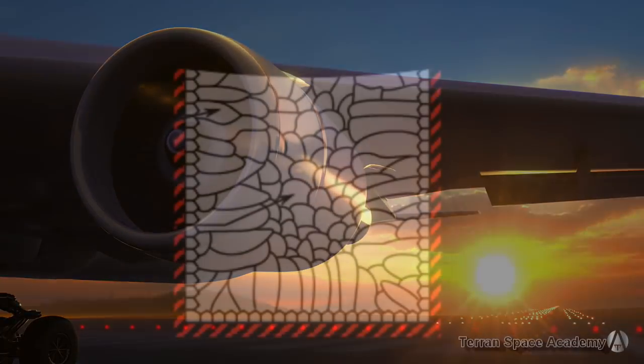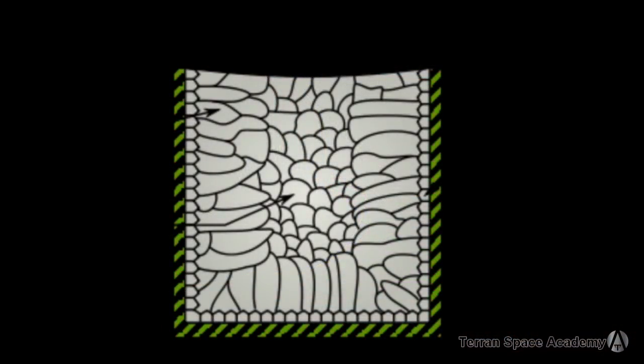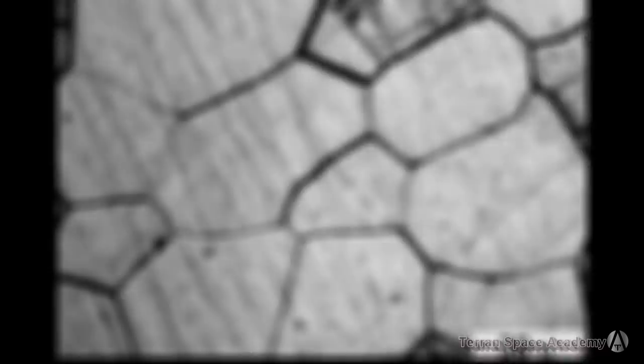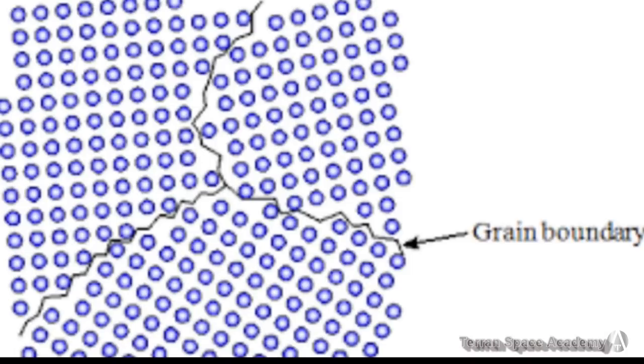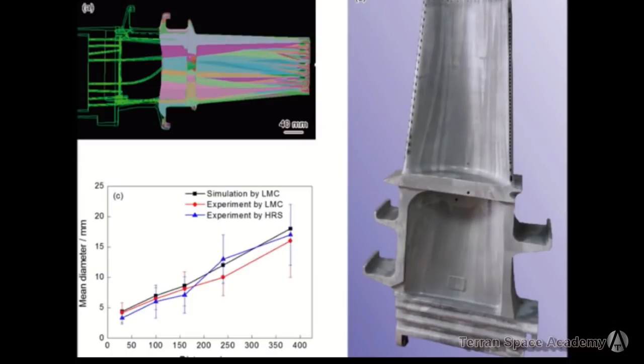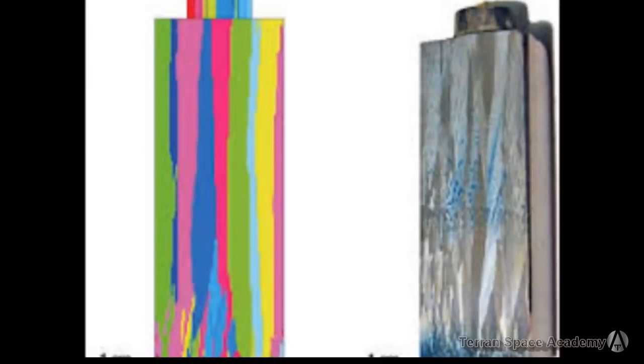Now, crystals form as alloys go from molten to solid. These crystals are just tens of microns across and are randomly oriented. At high temperature and stress, these crystals start to slide against each other, and any impurities create weak points between crystals. This is what causes creep. The engineers and metallurgists soon started finding ways to make all the crystals line up in one direction, with their long axis in line with the stress.